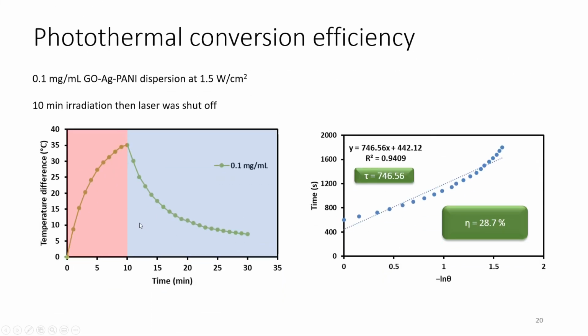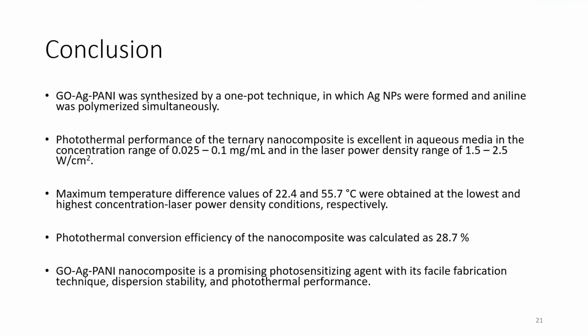This figure is the heating and cooling curve of 0.1 milligrams per milliliter graphene oxide silver polyaniline dispersion at 1.5 watts per square centimeters, and from the cooling data we plotted time versus minus natural logarithm of theta to calculate photothermal conversion efficiency as 28.7%.